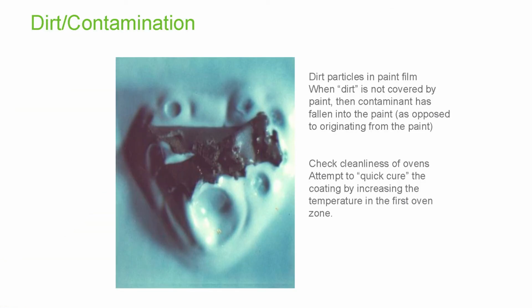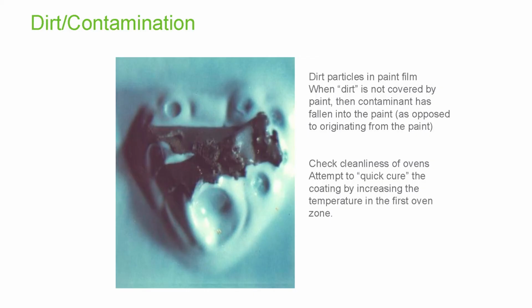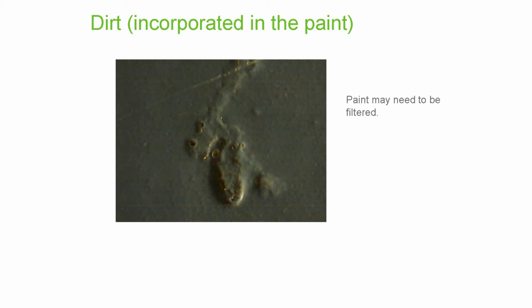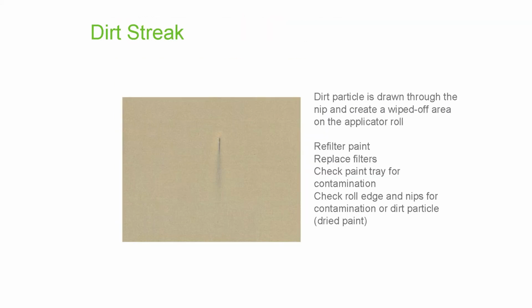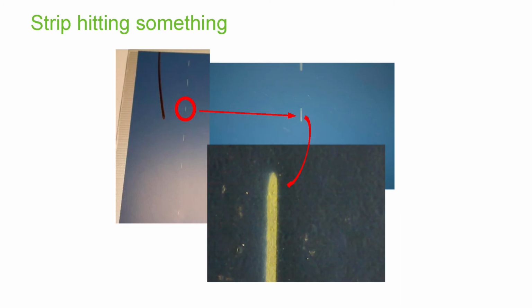Dirt in paint, well, this is just something that is a natural event. The paint companies do a pretty good job cleaning up dirt, but there's dirt on coil lines, and probably you're running the paint through a filter bag anyway. But this happens occasionally. It happens more likely, by the way, if you do not have a coater room that's using filtered air. So you always want to watch out for fugitive particles dropping in. And we have plenty of pictures of paint and dirt streaks.